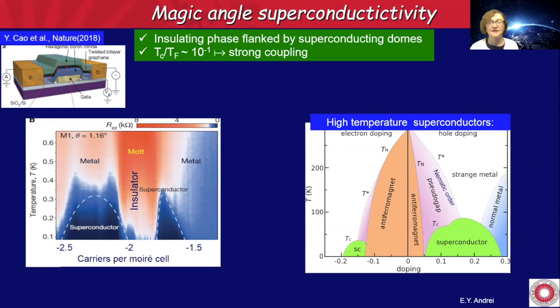In the high temperature superconductor, you have an insulating phase flanked by 2 superconducting domes. Another important factor was that the critical temperature divided by the Fermi temperature is relatively large. It's similar in both systems, which means that we have strong coupling between the electrons. The glue that holds them together and makes the superconductivity is quite strong. And